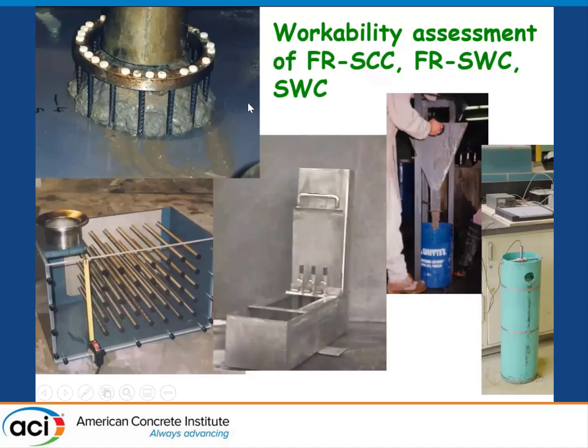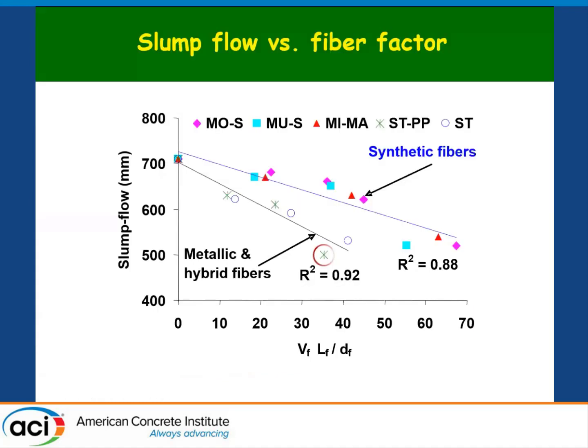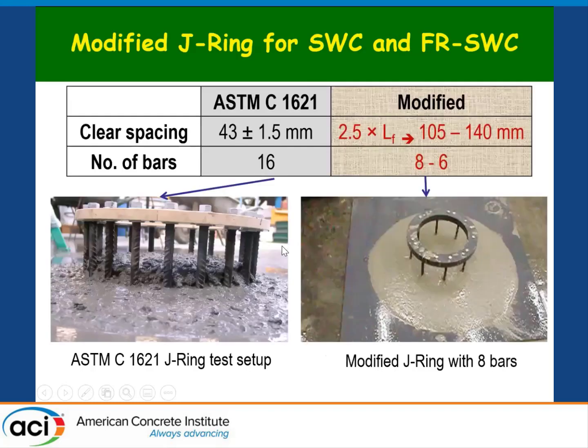Okay, so these are the test methods that we're all familiar with to evaluate workability of SCC. If you look at the slump flow and how it varies with the aspect ratio and the fiber volume, which is what we call the fiber factor, we can see that as we increase the fiber factor, we get a reduction of fluidity, as expected. And there are two relationships: synthetic fibers, because they can flow easily, can achieve higher flow than metallic fibers.